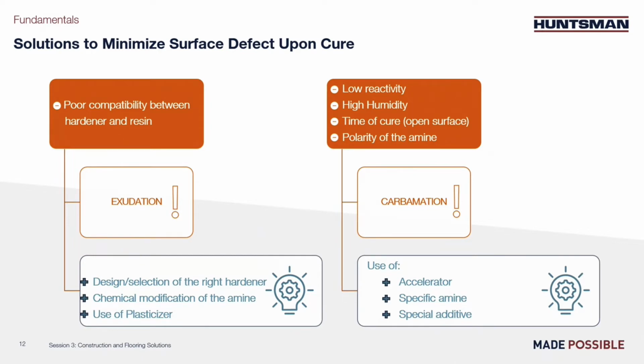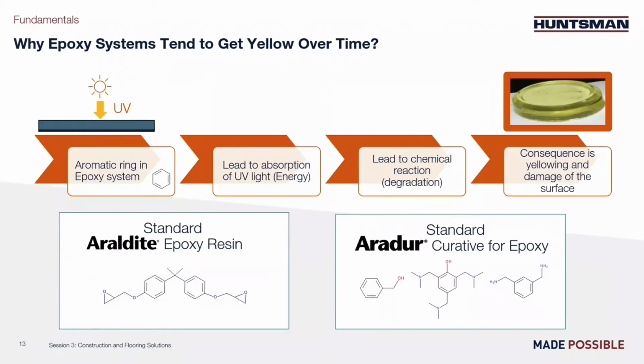Low reactivity, high humidity, and polarity of the amine can often lead to carbamation. To circumvent this phenomenon, we use accelerators, special additives, and specific amines. We will discuss further in the presentation using appearance tests, specific hardeners, and one additive actually.